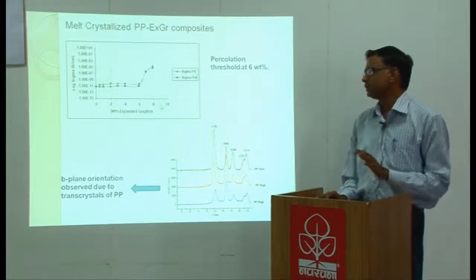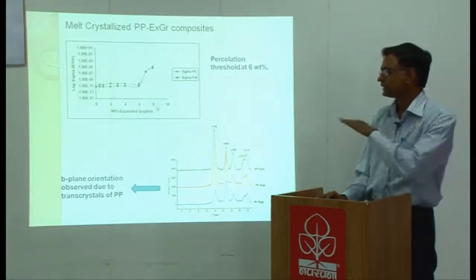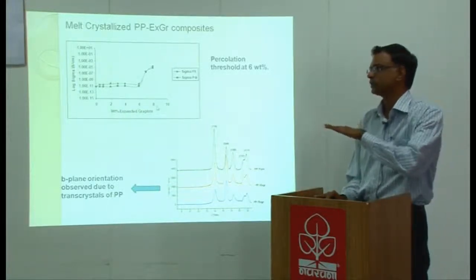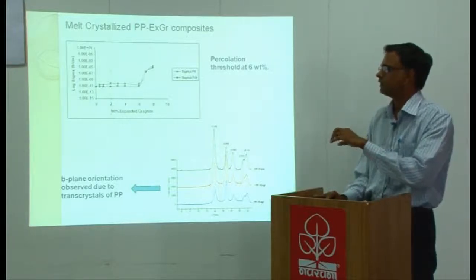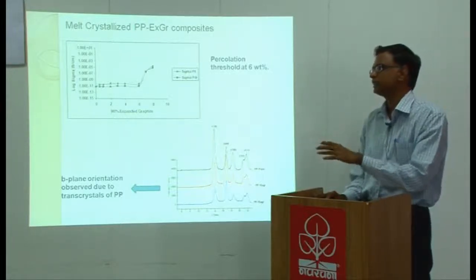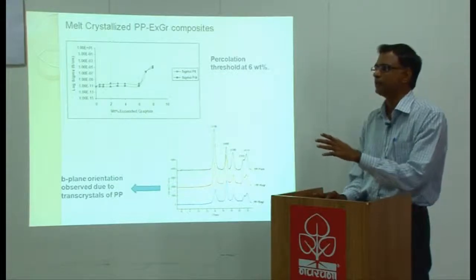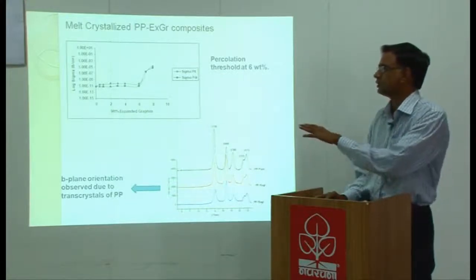If your melting temperature changes, the crystallinity of your base polymer changes which eventually affects your electrical percolation ratio. What I would like to say is that these aspects of basics need to be very thoroughly probed before we take the material or composite system for a particular application.